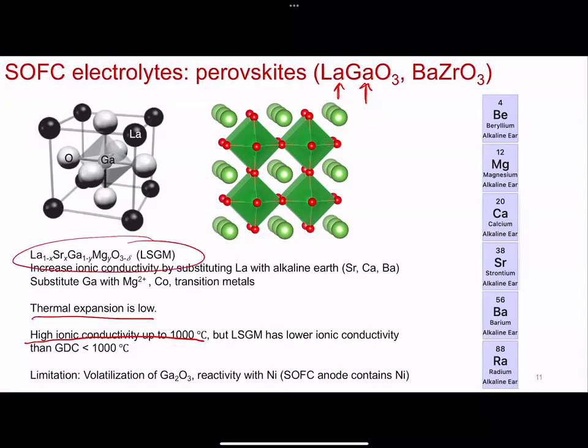So these kind of perovskites, this LSGM, lanthanum, strontium, gallium, magnesium oxide based compounds, they're a whole lot of fun to work with because there's such tunability. And when you make one change in these perovskite systems, the entire material changes because they're all, you could see in these perovskite materials, they're all corner sharing. So if you substitute one, you're going to cause correlated motions to occur. So you're going to get octahedral tilt, you're going to get rotations, and all these minor changes have huge implications in the macroscopic properties that you measure. So correlated motion in perovskites is a huge area of research. And so this is a rich field.